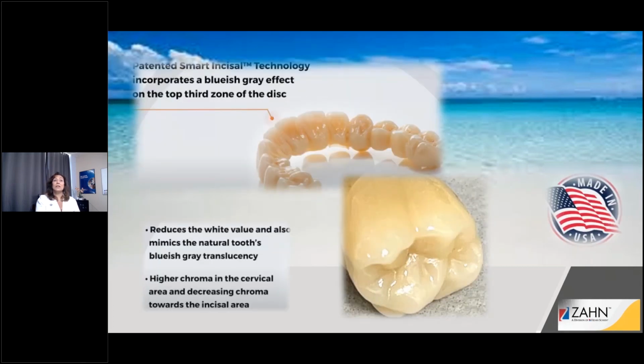The patented Smart Incisal technology. That's a pretty cool feature, with the blue and the gray powders that were added right into the disc. What that does is it reduces the white value. It mimics a tooth's natural translucency, and a lot of the times we're fighting a really high value with zirconia. You can get the shade right on the money, but that value is just a little too high. With this, you'll see that your value is going to be much more accurate. And again, you're able to control the intensity of chroma that you desire based on the sintering high temp that you select or finally decide on.